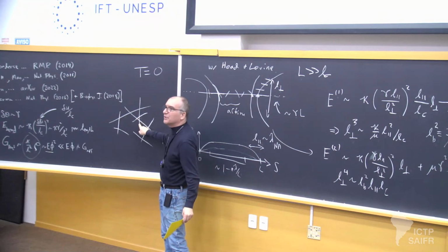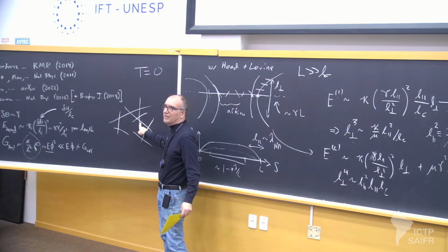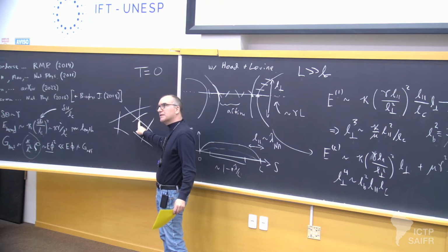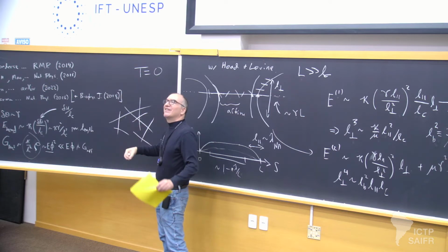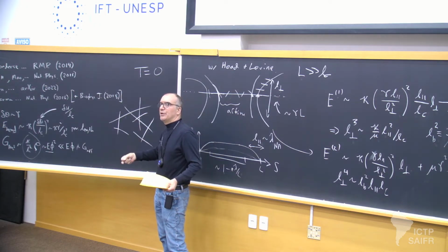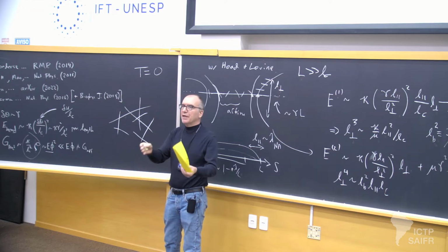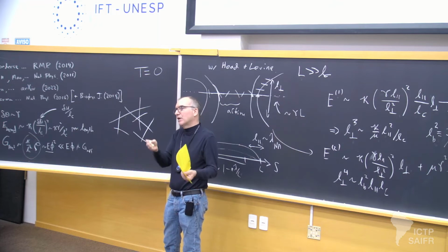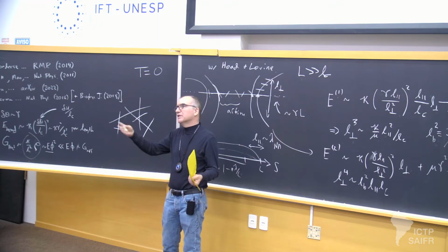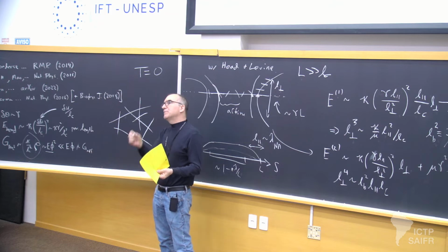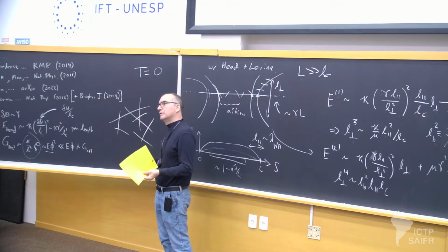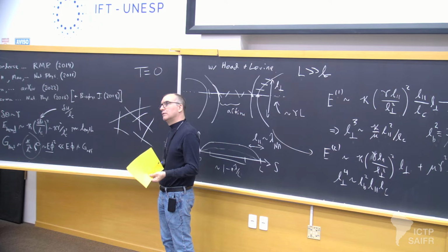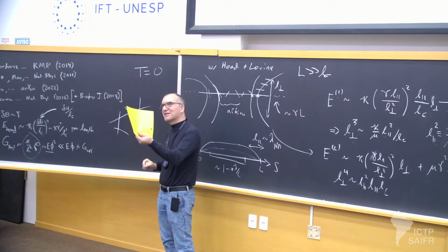Something does happen a bit like that here. When these get so close together, they effectively collapse. But these are rare events. So you could say that this looks like a z equals 6 connectivity point, but they're rare. Literally, the average connectivity, whenever anyone measures it for these fiber networks, is around 3.5. It never gets anywhere close to 6, except in special architectures. But we know that you do get rigidity. Exactly, and I'm going to try and explain why.